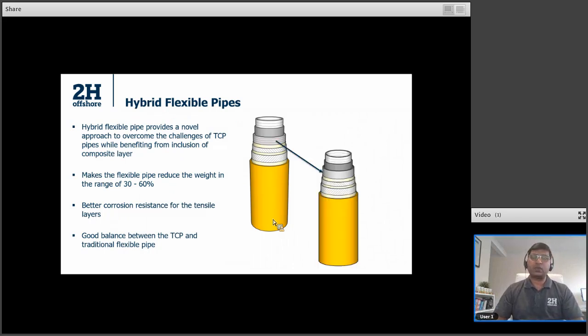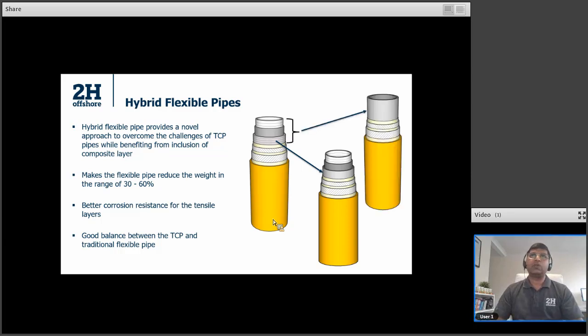So there's two variations where we can target the hybrid flexible pipe. One is to replace the pressure armor with a composite layer, because we have seen that the composite layer can also give you the same strength capacity as a traditional carbon steel structure. Or it's also possible that we could eliminate the first three layers of a traditional pipe, namely your carcass, your pressure sheath and your pressure armor, and replace with a composite structure.